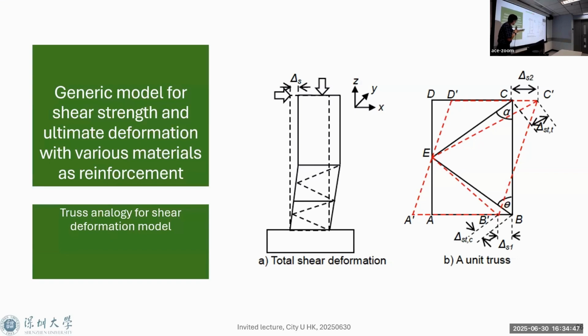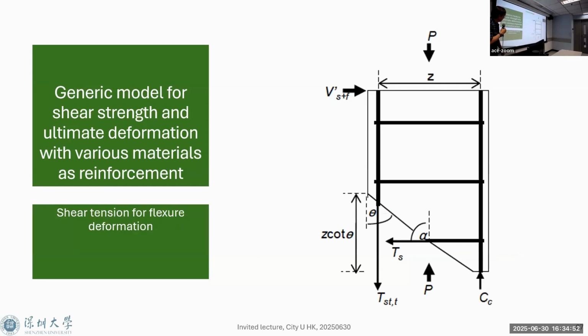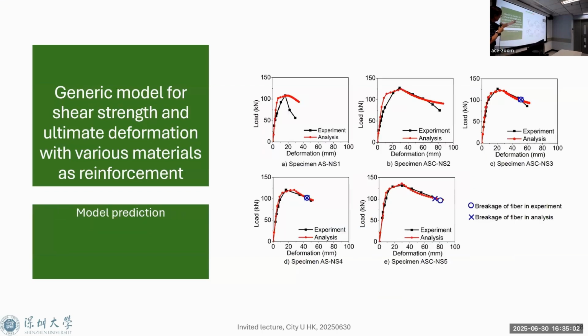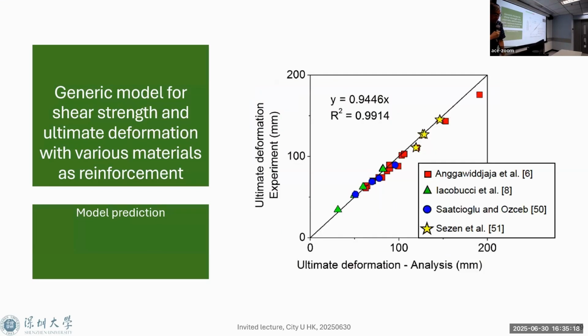And we also consider shear deformation utilizing a simple truss analogy. Then also we can consider tension shift in the tension reinforcement, which produces additional flexural deformation. Then this is a model prediction. So our model predicts, except in this case, quite nicely the post-peak behavior. So we can predict ultimate deformation, which is necessary for seismic design. And the prediction and the experimental result agreed.